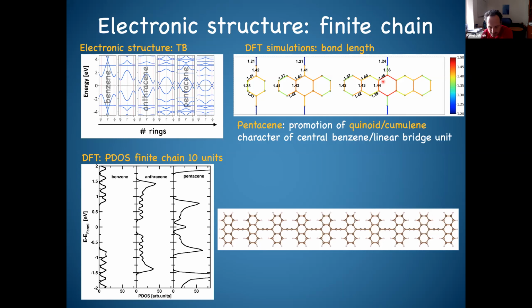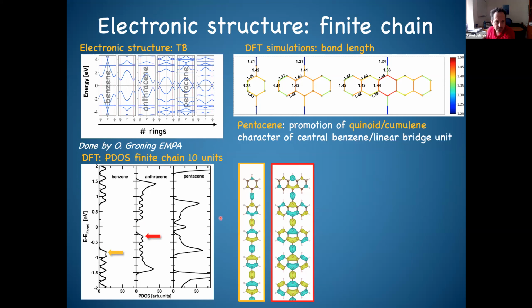Now I will look at the electronic structure of a finite system made of 10 units, and I will show you the density of states calculated for this benzene polymer, anthracene polymer, and finally pentacene. The anthracene polymer is plotted here, and you see there are no states at the Fermi level. This is the calculation with spin restriction. In the case of anthracene, we can go to the frontier orbitals, and they are delocalized overall. However, when I look at pentacene, I see that there is something at the Fermi level, so the system seems to be metallic.